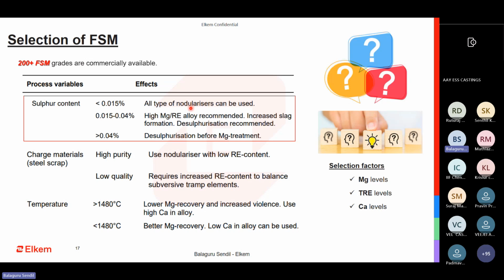Not only that, the nodule count you see will also be small and uniformly distributed, which is a very ideal situation. So sulfur should be the major factor to determine how much magnesium I want. The limit is more than 0.040, but typically in Indian conditions, if it is more than 0.020, we ideally prefer desulfurization. This is the case when you're duplexing, bringing metal from the cupola and then pouring; then we would recommend desulfurizing before doing ductile iron treatment.